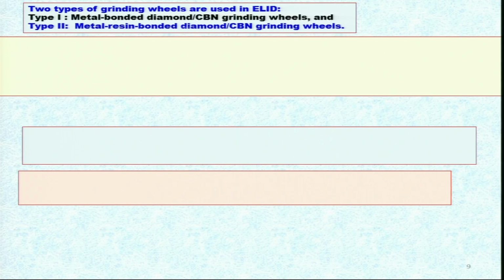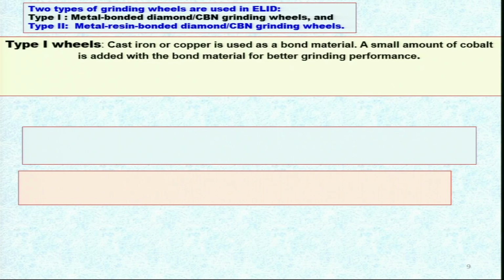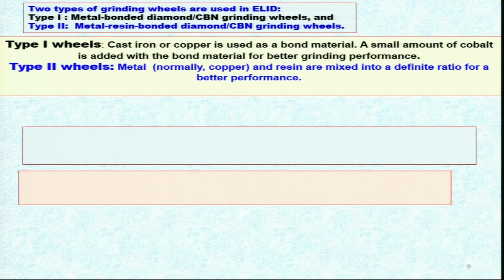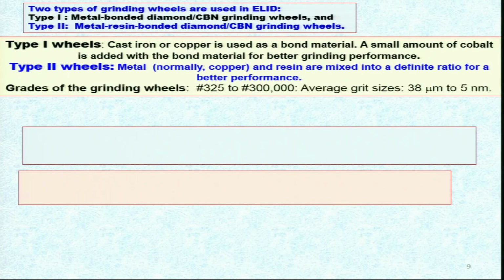Two types of grinding wheels are used in ELID. Type 1, metal bonded diamond or CBN, that is cubic boron nitride grinding wheels, and type 2, metal resin bonded diamond or cubic boron nitride grinding wheels. Both types are used depending upon the workpiece material and other compositions. In type 1 wheels, cast iron or copper is used as a bonding material. A small amount of cobalt is added with the bond material for better grinding performance. In type 2 wheels, metal, normally copper, and resin are mixed in a definite ratio for better performance.